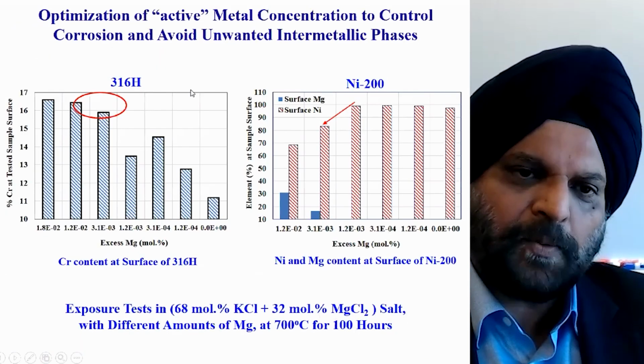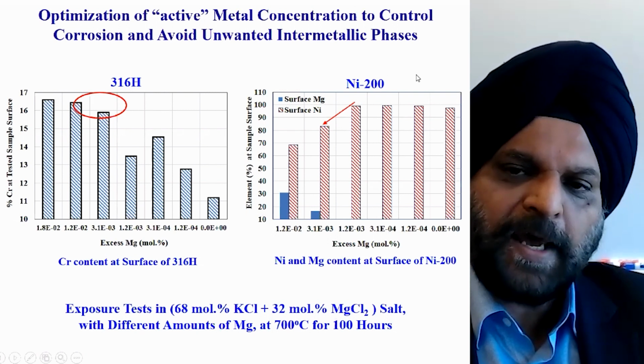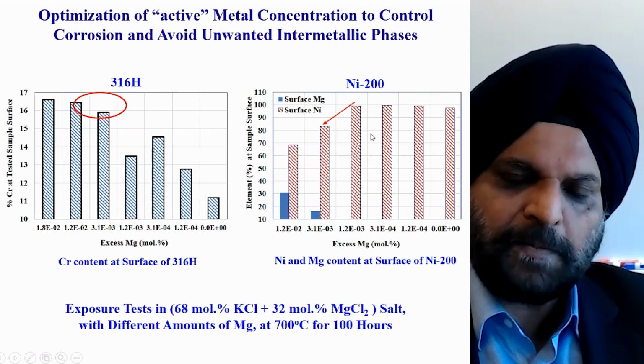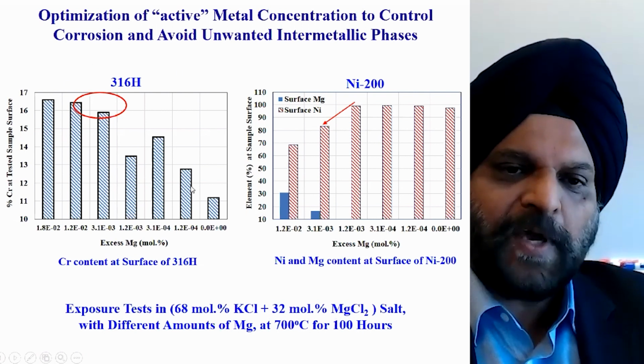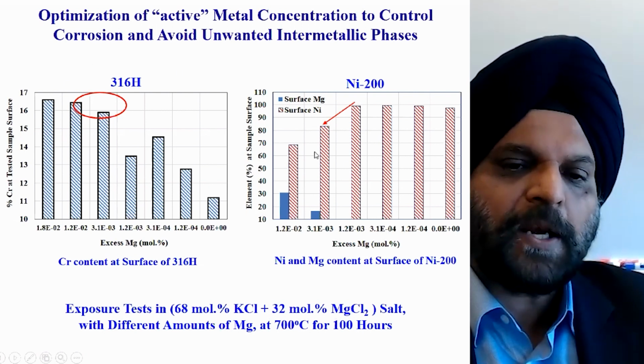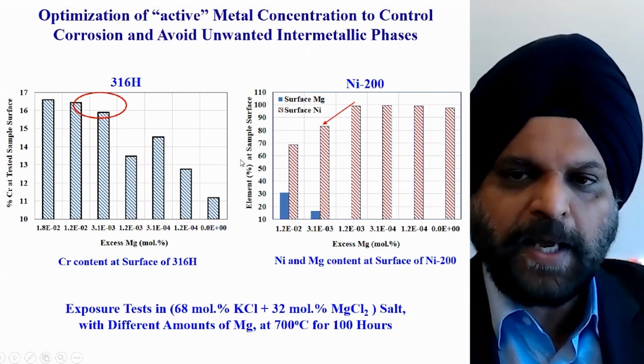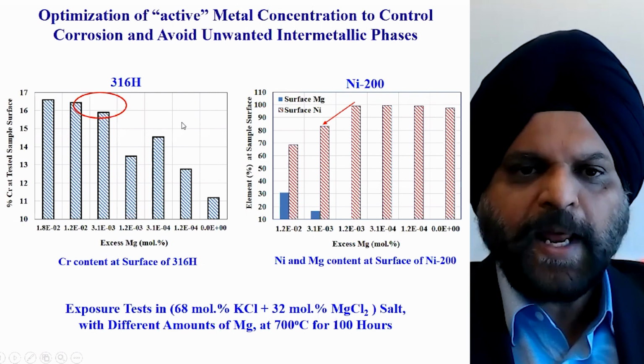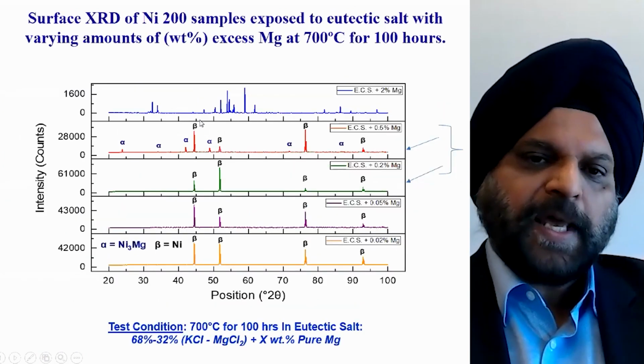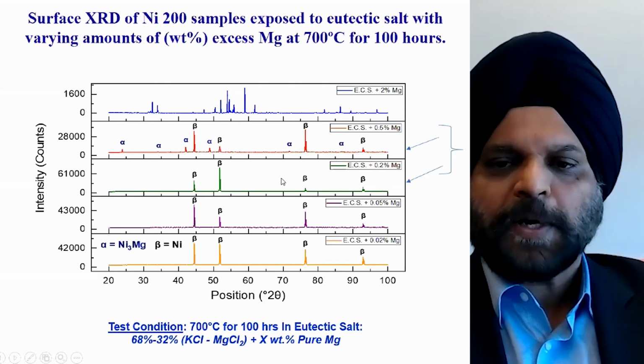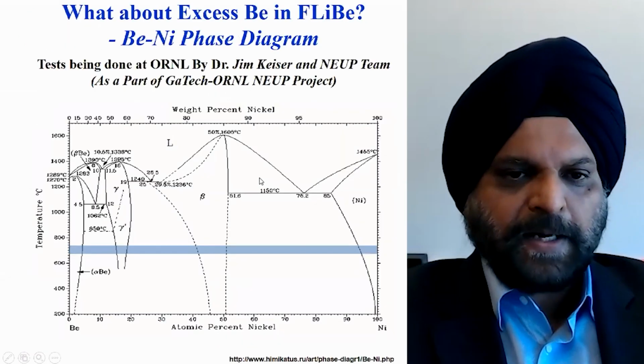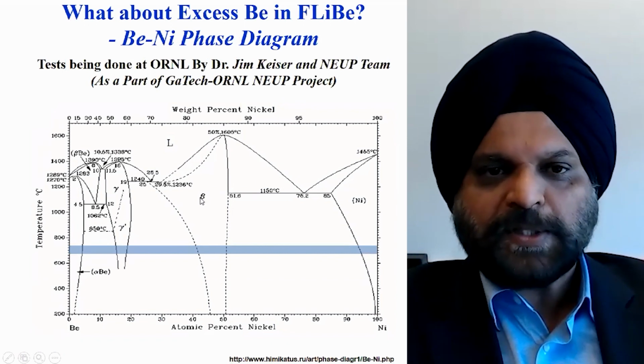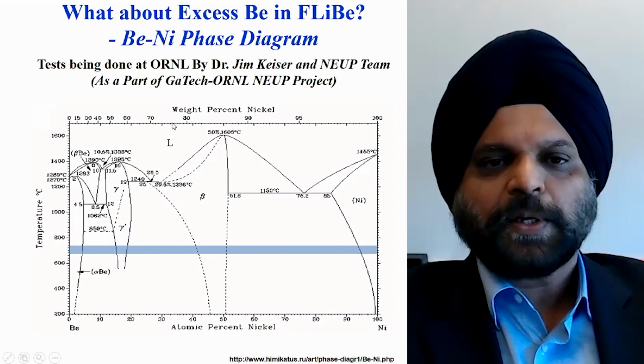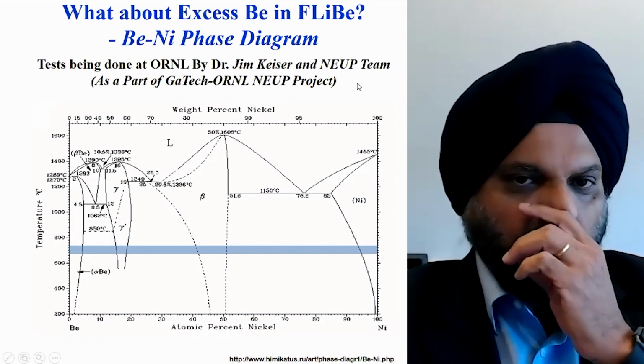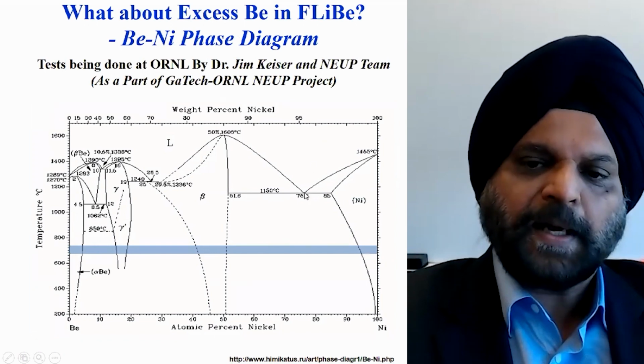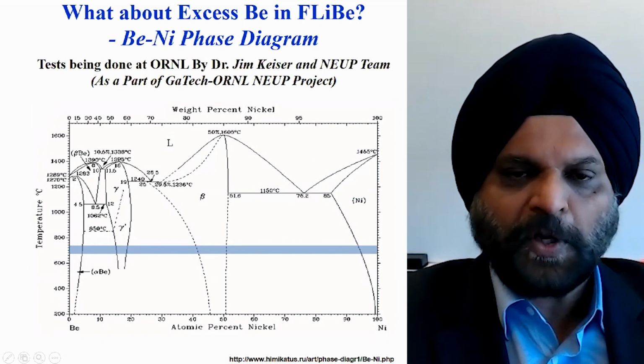So we wanted to make sure that we can control corrosion, but not have nickel-magnesium intermetallics. We looked at various concentrations and found that you can optimize where you reduce corrosion and do not have nickel intermetallics form. One has to be aware of that, and we confirmed it using X-ray diffraction, and you can optimize how much excess element can be added. The other concern was that FLiBe will do the same thing if we add beryllium in there. So Dr. Jim Keiser and his team at Oak Ridge, as part of our NEUP project, are right now doing these tests for FLiBe as well.